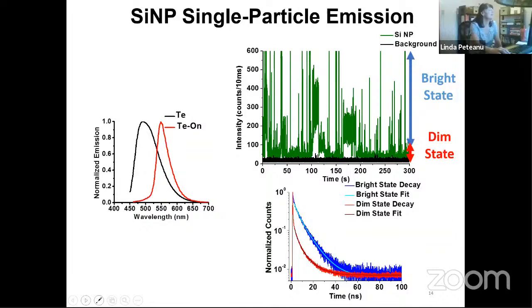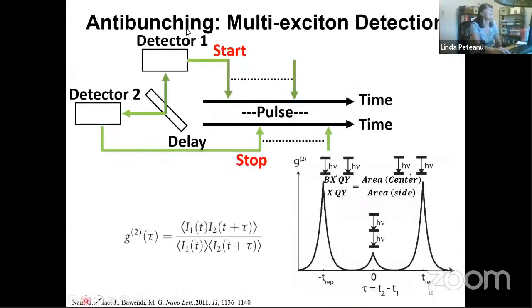So there are other ways of looking at the single versus biexcitonic nature, or the potential for that in these systems, and that's known as using anti-bunching. This methodology, the use of this in assigning biexcitonic states, was pioneered by Moungi Bawendi, and it basically uses the same setup that I talked about earlier, where you have two detectors on which you split the emission. In one case, the first photon acts as the start photon for data collection, and a second photon that arrives acts as the stop photon.